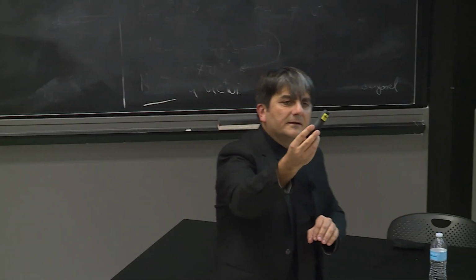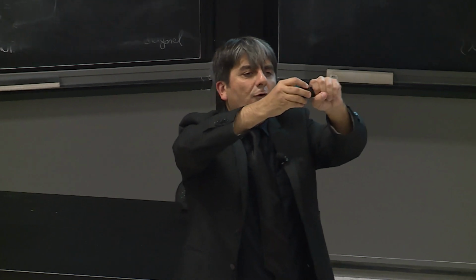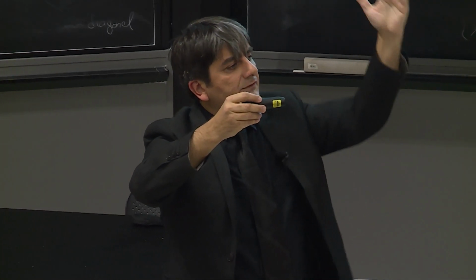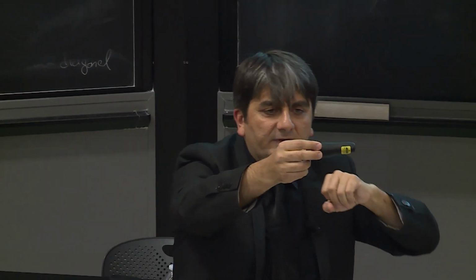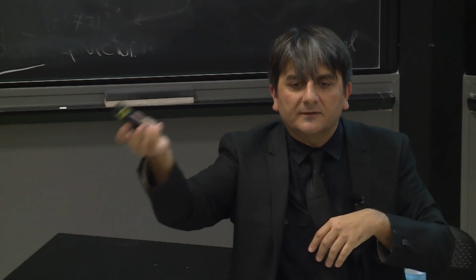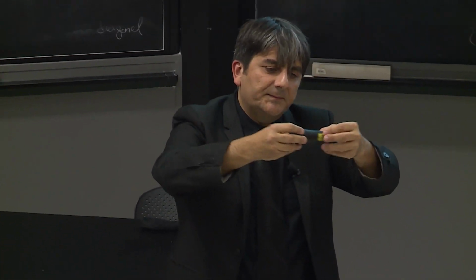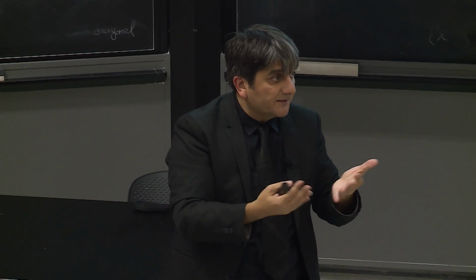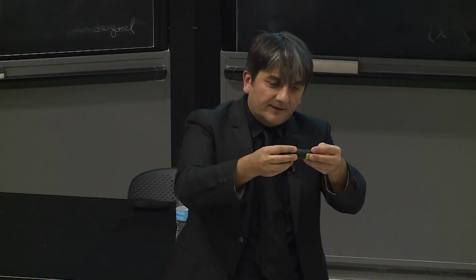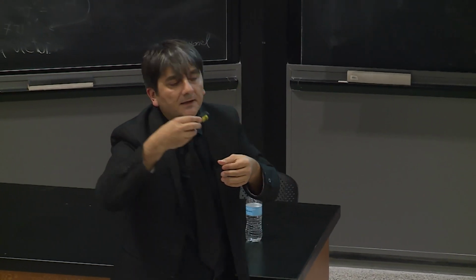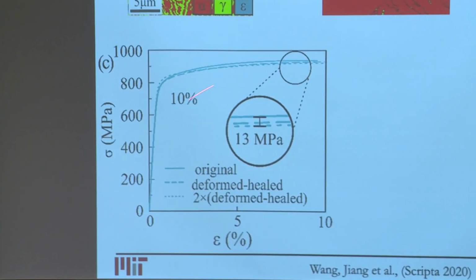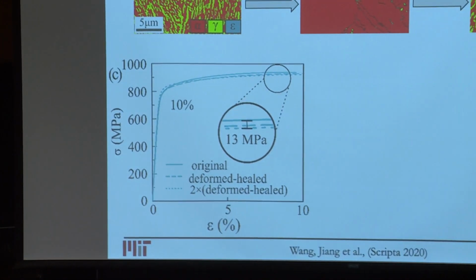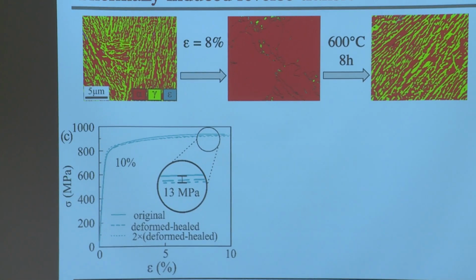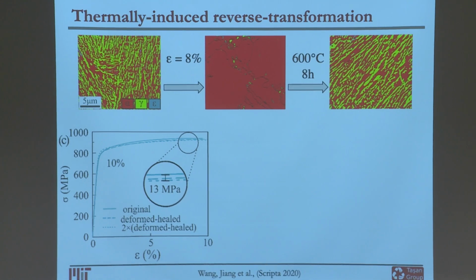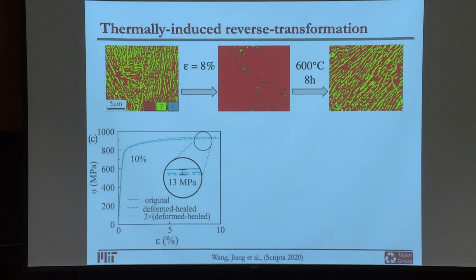So you take this material, you deform it to 10%, you record your stress strain curve, then you take it off the clamp, do a heat treatment, come back, and repeat the same test. And basically, you get the same mechanical response. And then you stop at 10% again, do the heat treatment again, and you get the same response. So it's basically 3 curves on top of each other, which demonstrates that the material can go back to a very similar state to the starting microstructure.